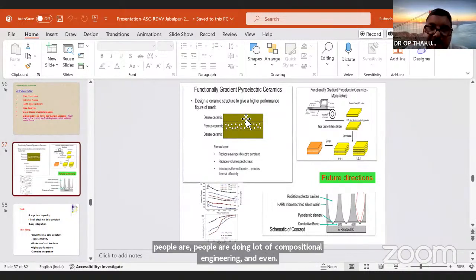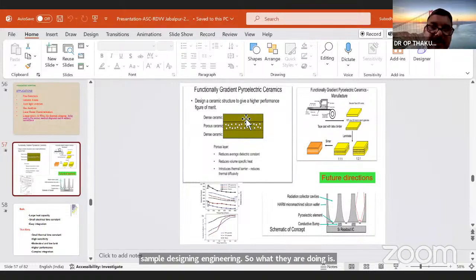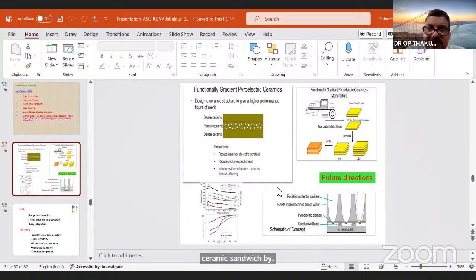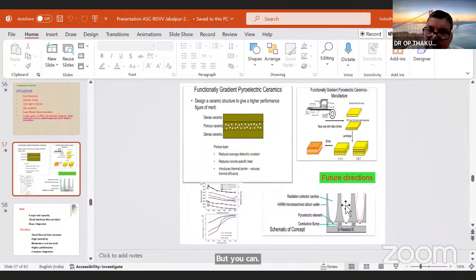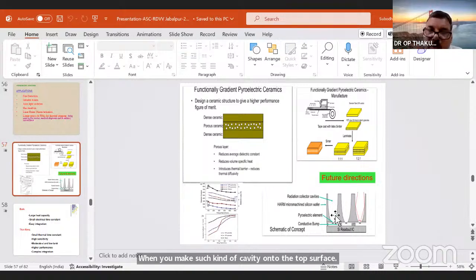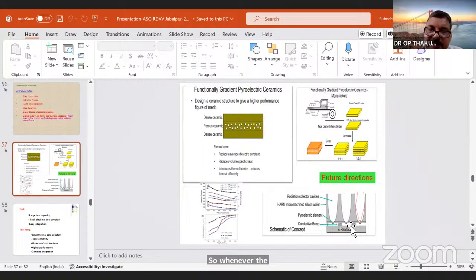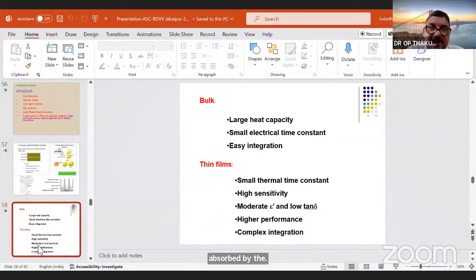For pyroelectric ceramics, the dielectric constant should be very, very low. For that, they are putting some porous ceramic sandwiched by two dense ceramics. That will decrease your dielectric constant. There are several different mechanisms, like in this photograph, you see they are putting a reticulated kind of structure by etching the top surface. When you make such a cavity on the top surface, you are able to absorb more and more IR. Whenever the IR radiation falls, it will be fully absorbed by the surface of your sample. So this is another advantage.